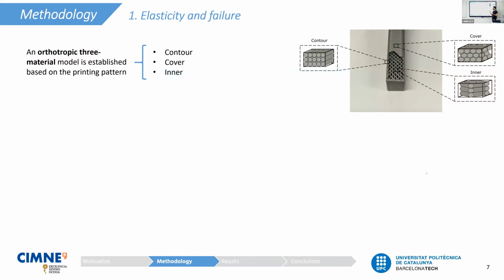We distinguish mainly 3 different printing patterns in fused filament fabrication components. The first one is the aligned filaments, which we call the contour zone, the zone around the component that conforms the lateral walls. Then we have a second printing pattern called the crossed filaments, which is the cover zone, meaning the top and bottom covers of the component. And then we have a third printing pattern, the inner zone, which can be conformed by many different printing patterns and many different infill densities.